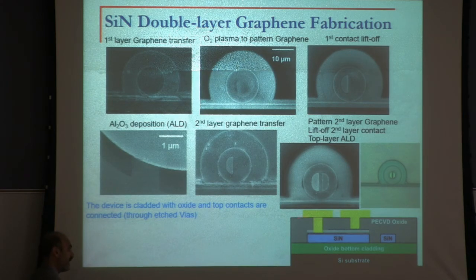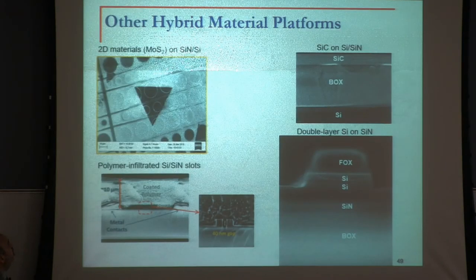Now, we are still working on this because the sheet resistance of graphene is higher than what expected, but that's another material platform that we have developed, being able to transfer graphene by wet transfer technique, put oxide in between, and then combine it with silicon nitride technology. These are some other hybrid material platforms.